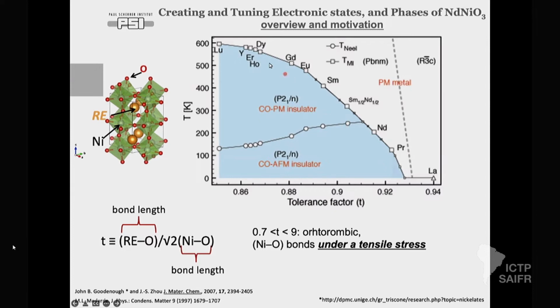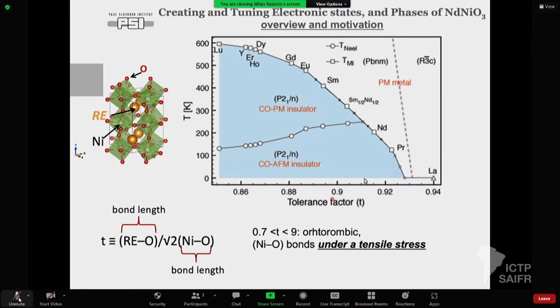So what you could see here, this is a pretty complex diagram, and you could see this is the rare earth element right here in the nickelate, and then you have the element which supports this crystal structure. But an important parameter in nickelate is the tolerance factor. Tolerance factor basically is the ratio between bonds, which is the rare earth oxygen bond and the nickel oxygen bond. Depending on this ratio, you have a phase transition, that's clear.